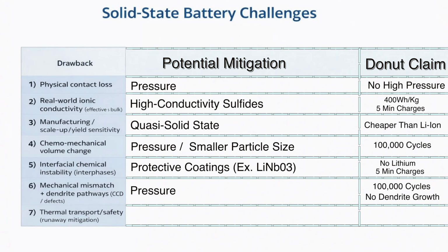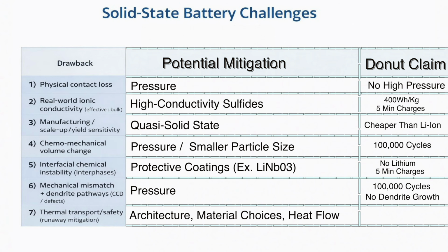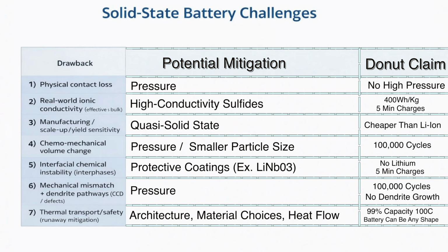Finally, thermal issues don't go away with solid electrolytes. Instead of potential for fire, which you get with liquid electrolytes, you get potential for durability failure. Thermal mitigation in solid-state batteries is primarily an architectural problem. Materials and structures must create controlled heat flow paths and suppress damaging temperature gradients. Donut says 99% capacity at 100°C, and the battery can be any shape, so heat flow problems could have potentially been solved in a novel way. Donut's claims are being thrown around as if they are the holy grail, and there's a reason for that.